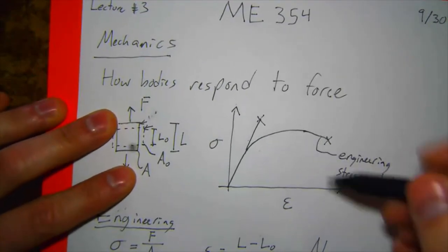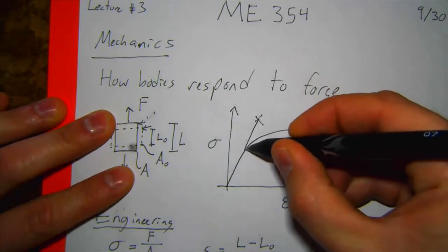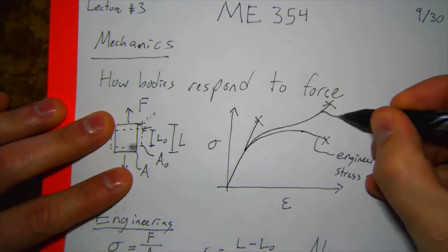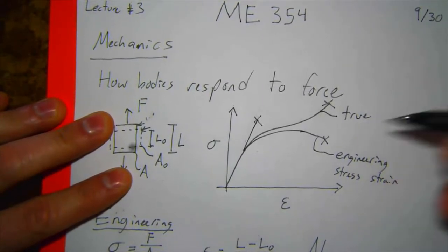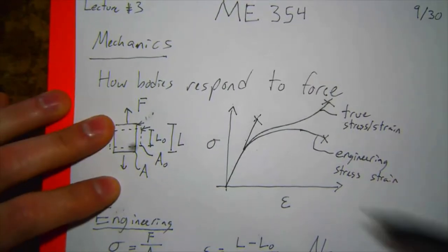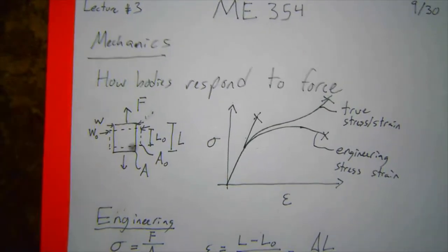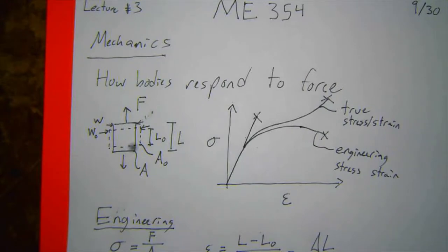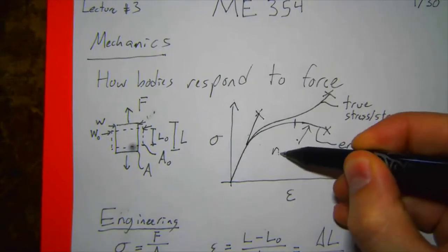So what this looks like in our stress strain response, if we were to calculate it using the true, or the actual, area instead, is that here I would have my force continuously increasing. So this now would be a true stress strain response. So actually this drop that we see in normal engineering stress strain curves is because we're not accounting for the fact that area is getting reduced. So often this drop here is due to necking in the sample.